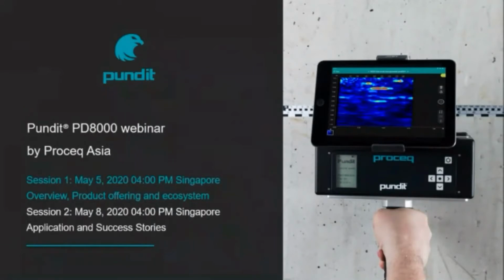So definitely for objects like voids, you're talking about typically the size of a table tennis ball, which gets quite difficult to see with real precision. Voids the size of a tennis ball you can see, but we can detect smaller objects. Rebars, definitely we can detect much smaller size rebars.